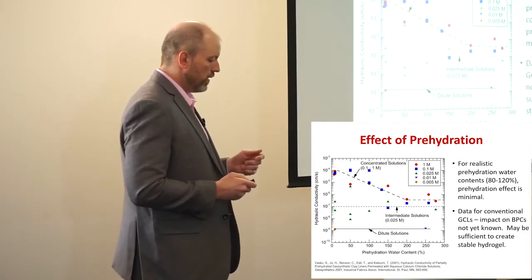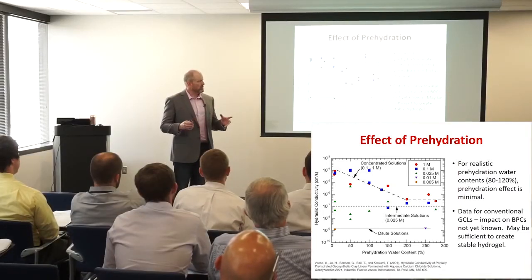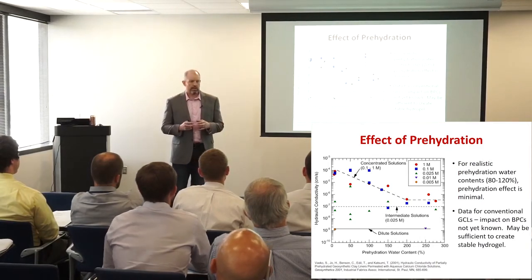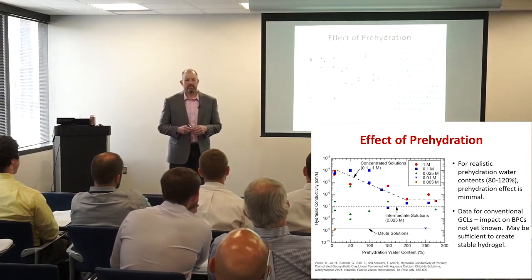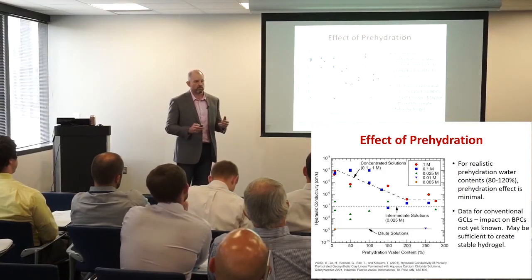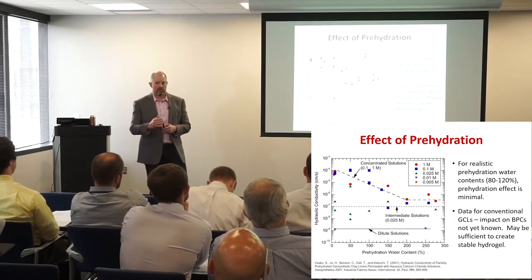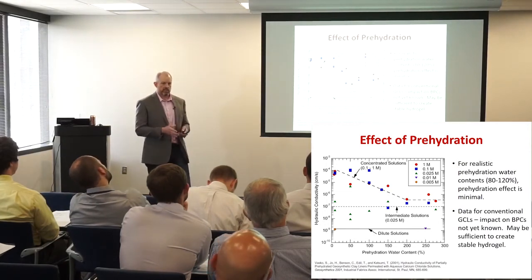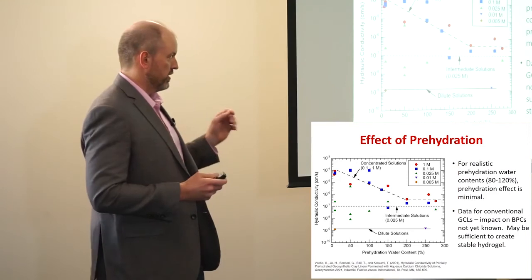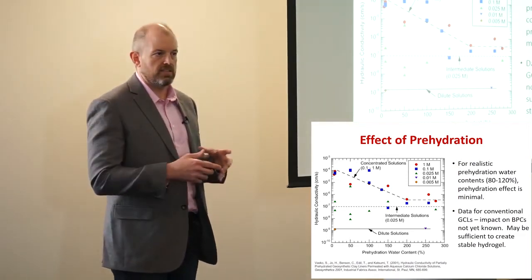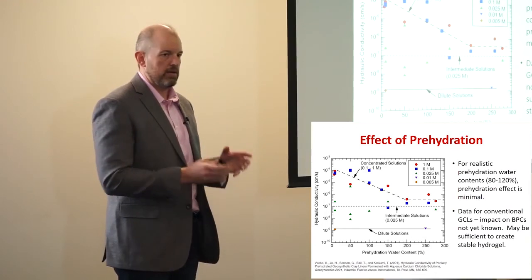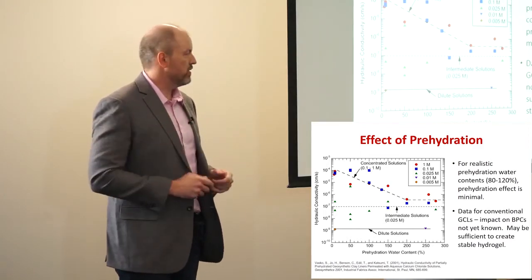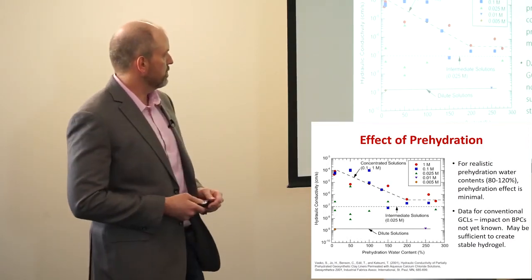It's possible to prehydrate the GCL with water in the laboratory per the ASTM method, but this is not a conservative practice — eventually an ion exchange occurs. The conservative approach when setting up these programs is to expose the product directly to the leachate it will encounter. I'll show a data series demonstrating how these products behave when exposed to leachate from the start, and how with time you can arrive at a proper solution.